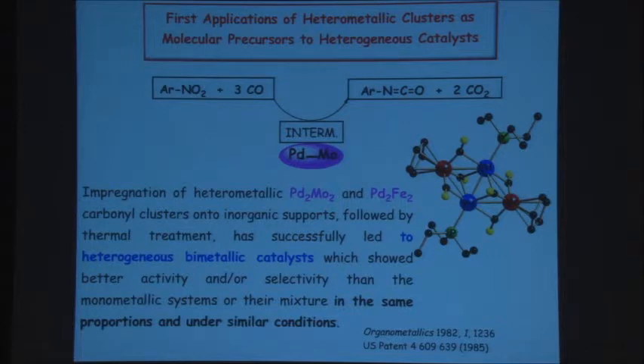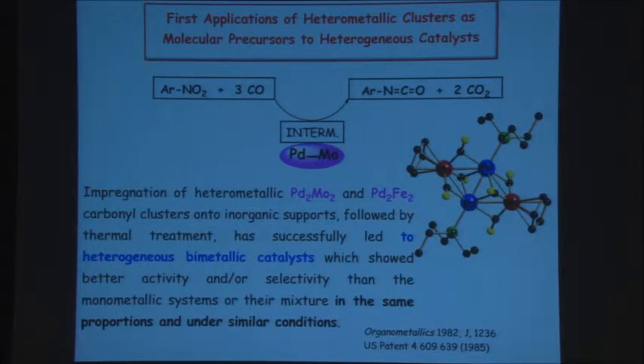So when I came up with the idea to use this guy, to put it on silica or alumina, thermally activated to decompose it, and look at the metal particles resulting from the decomposition, a lot of colleagues said, Pierre, you're absolutely nuts. You spend your time trying to make nice molecules, now you want to destroy them thermally. Are you totally crazy? So, if you get something more exciting at the end of the day, what's wrong with that? Nowadays, lots of groups worldwide are using this approach to generate nanoparticles. So sometimes, you may have a crazy idea, but which turned out to be a fruitful idea.